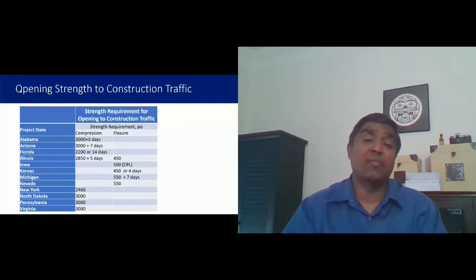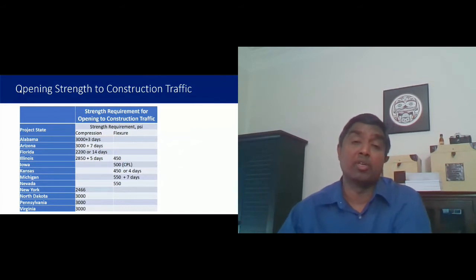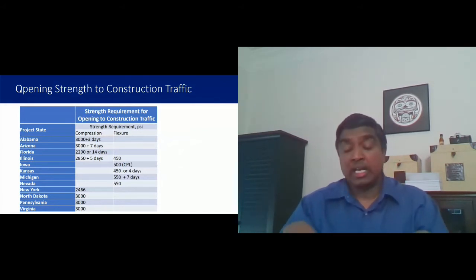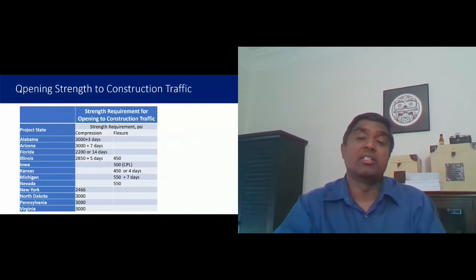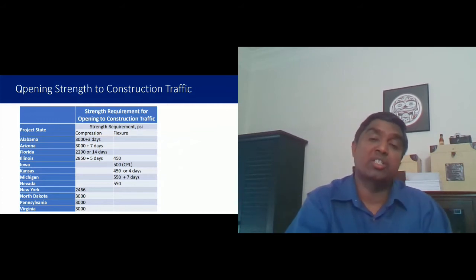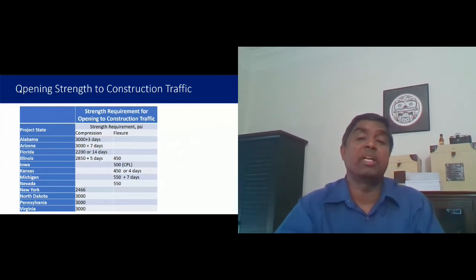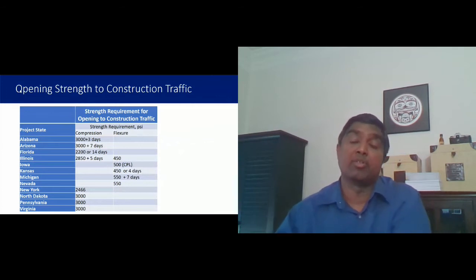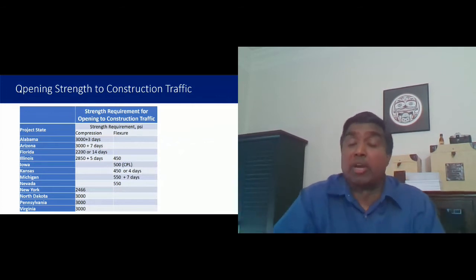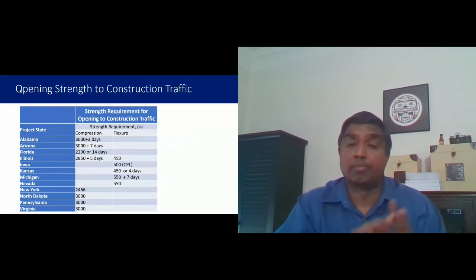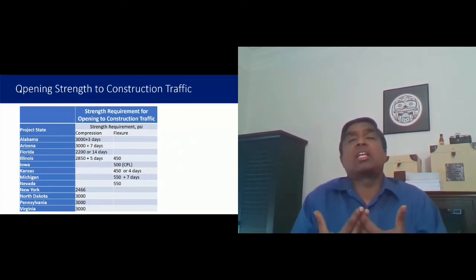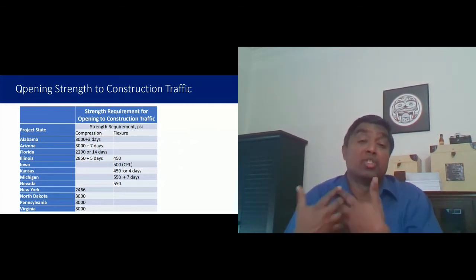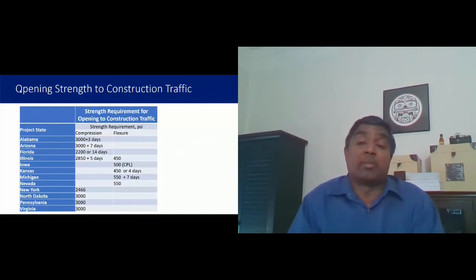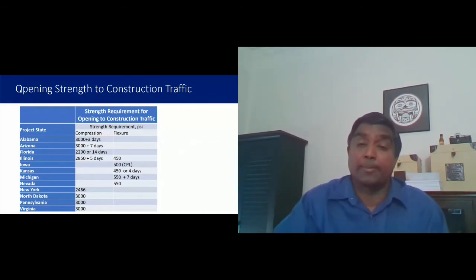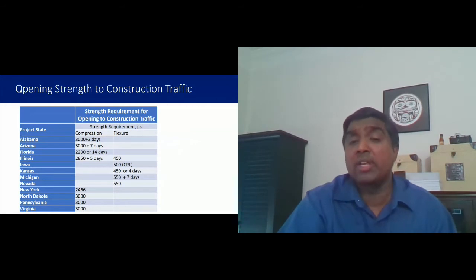And secondly, if you're using lab cured beams or cylinders, that's even worse because the weather conditions or the curing temperature that the structure or the pavement is being exposed to is completely different than lab cured beams or cylinders, which are typically exposed to the same temperature throughout. So in reality, we are using these cylinders and beams and assuming that they represent the pavement, but they really do not. So, what can we do about it?